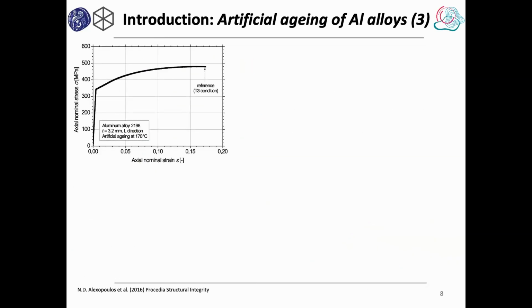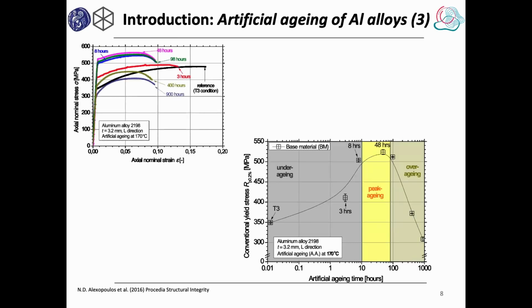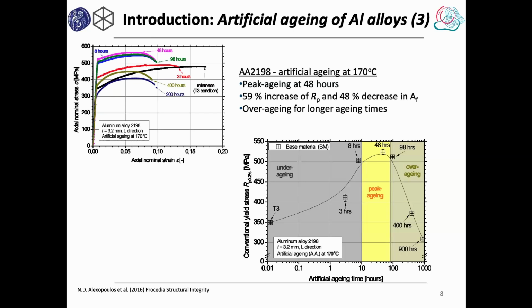And this is, for example, how the properties of the base material look like for different heat treatment conditions. We have peak aging, for example, achieving the maximum strength after 48 hours, the maximum yield strength that can be achieved. After that, we will have overaging, and it can be achieved by different combinations of time and temperature. And the idea was to find optimal process parameters for welding of this alloy using laser beam welding, and optimum parameters for the post-weld heat treatment to find a good balance with regard to mechanical properties of the weld.